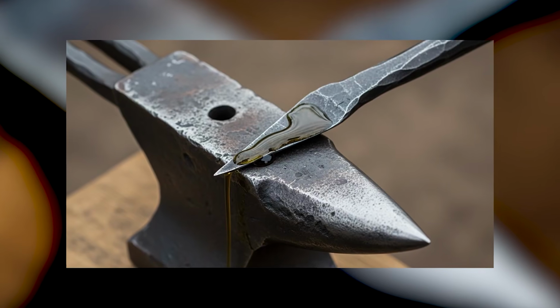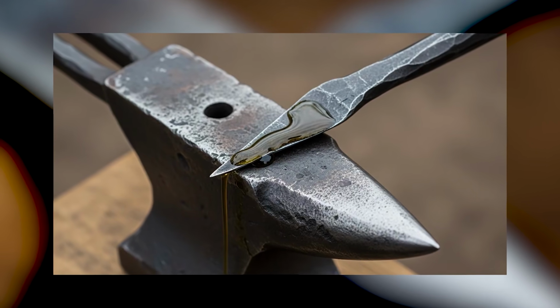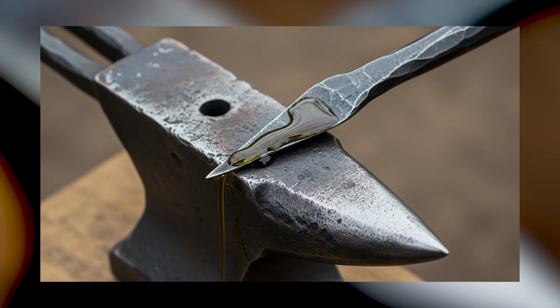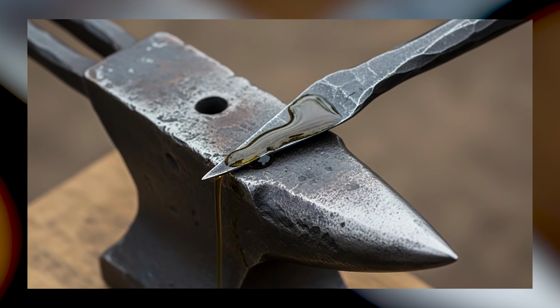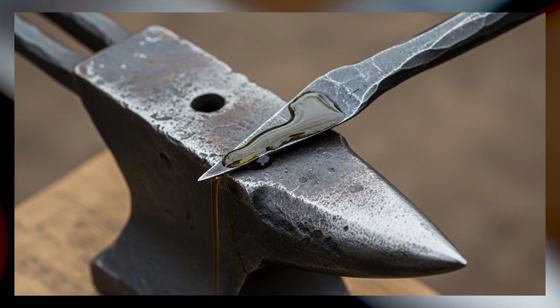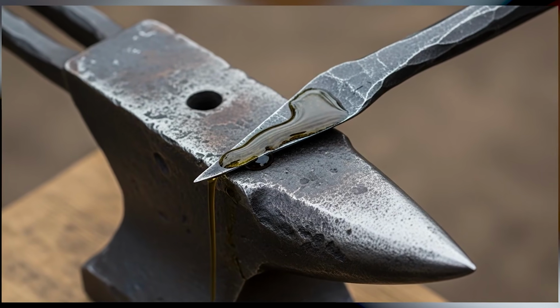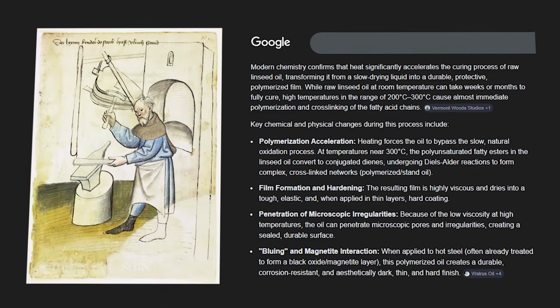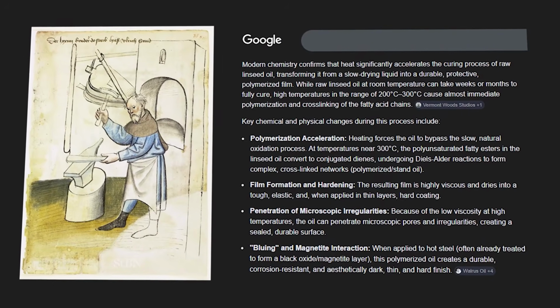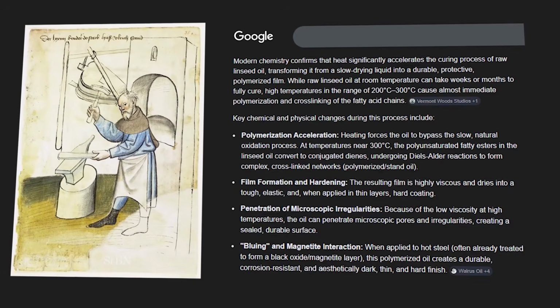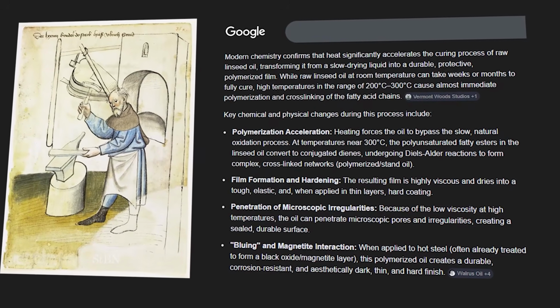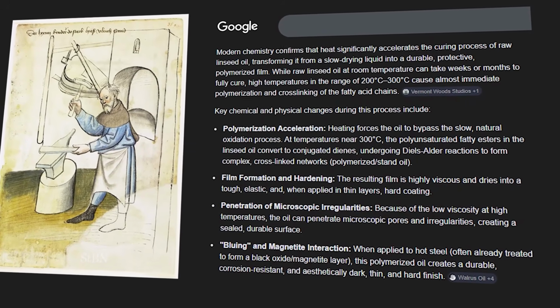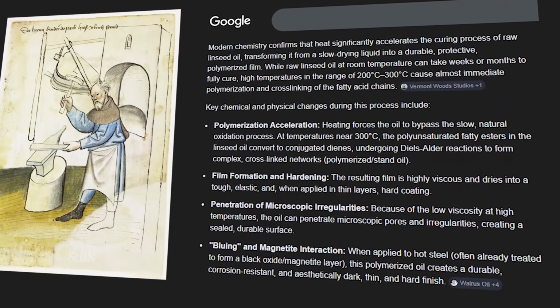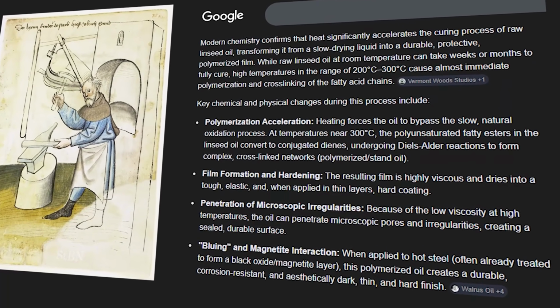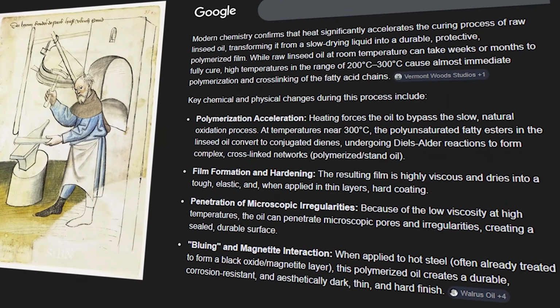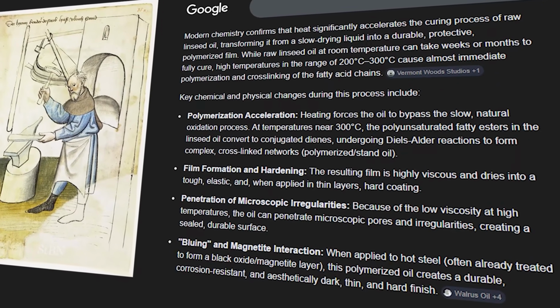Medieval blacksmiths discovered that wiping linseed oil onto iron while it was still warm from the forge, not forge hot, but warm enough that the oil smoked slightly, around 200 degrees Celsius, produced a hard, dark finish that resisted moisture and corrosion far better than oil alone. What they did not know, and what modern chemistry has confirmed, is that the heat dramatically accelerates the polymerization process. At room temperature, raw linseed oil takes weeks or even months to fully cure. At 200 degrees Celsius, the cross-linking begins almost immediately. The result is a thin, hard film that fills every microscopic pore and irregularity in the magnetite layer beneath it.